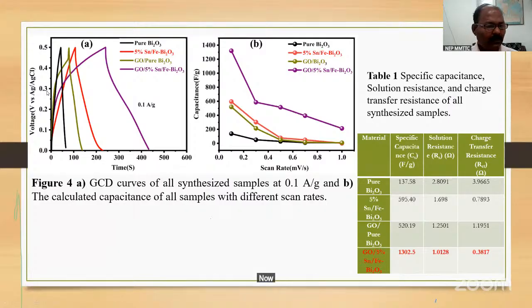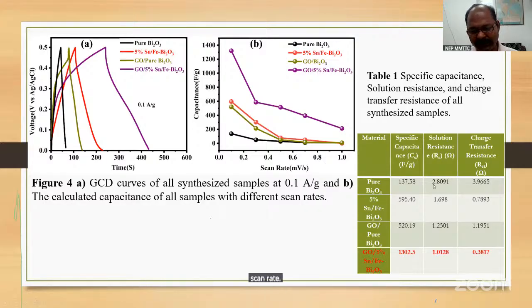Now you see here what is important. This is the galvanostatic charge-discharge curve of all synthesized samples at 0.1 A per gram, and the calculated capacitance of all samples at different scan rates. Now you see here, for this GO 5% tin iron bismuth oxide, the specific capacitance is 1300 and 2.5.